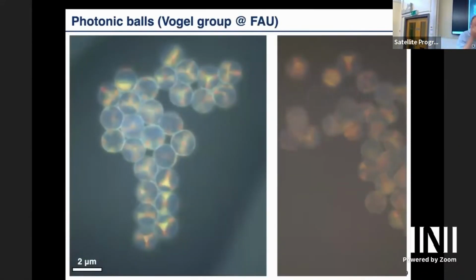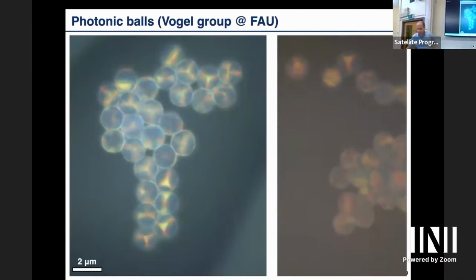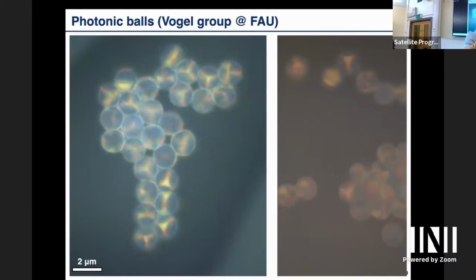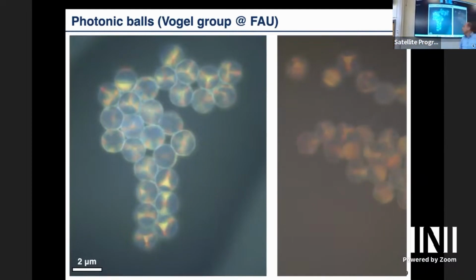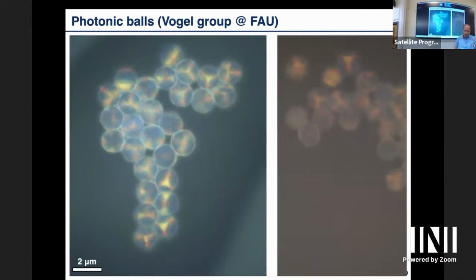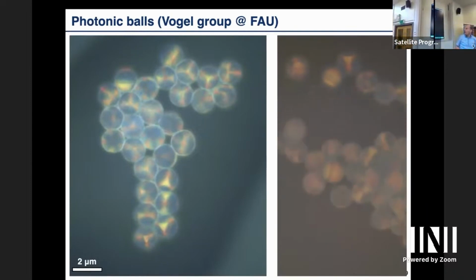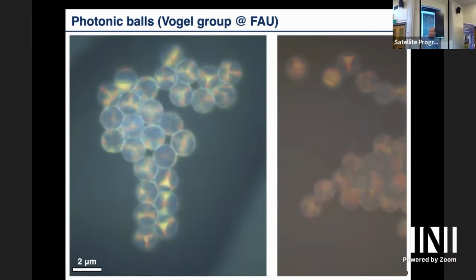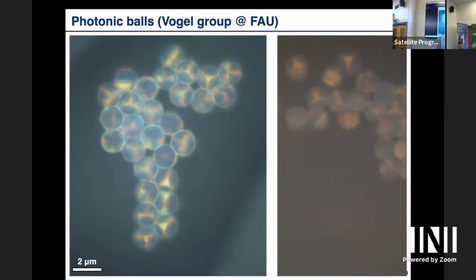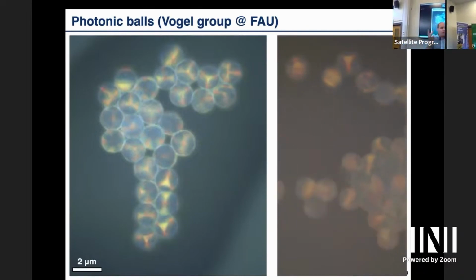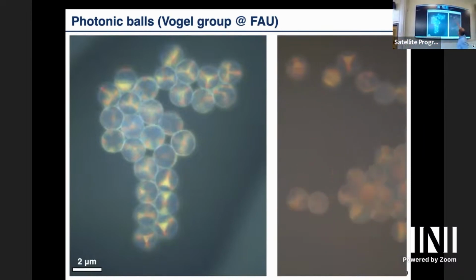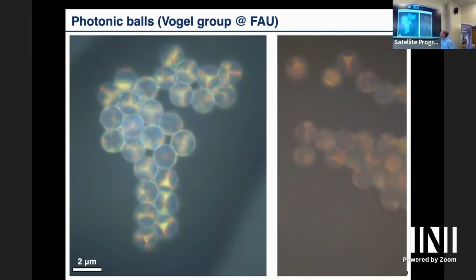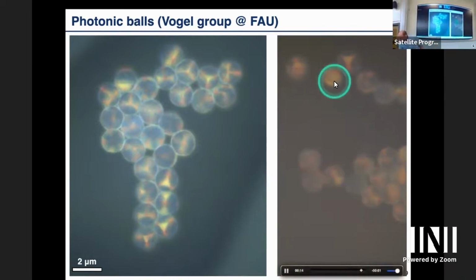Maybe just the last part: we can also, or my colleagues can, look at photonic color. I will put these small balls under the light microscope, and then you look. Here's a static image. Here's a video. You look at these clusters, and they look a bit like marbles. We have a very characteristic sign, like here's a threefold, twofold sign. That has to do with the fact that in an icosahedron, here's fivefold symmetry. Icosahedral has twofold, threefold, fivefold directions. Plus, here in the movie, you see also some other clusters. For example, maybe if I go over here, this is one with stripes.